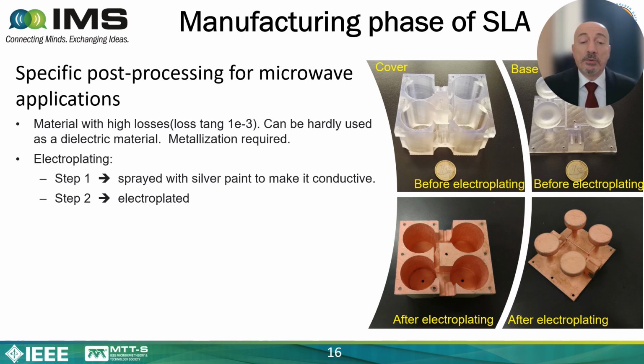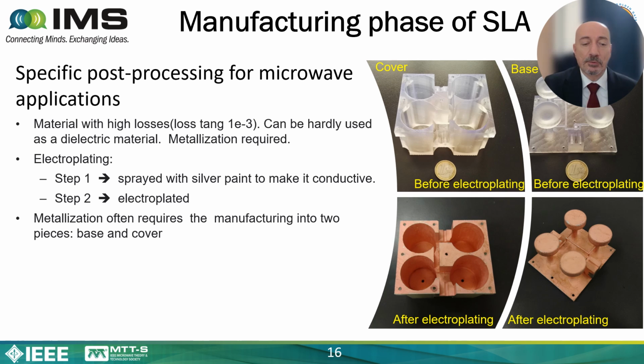Why do we also use the electroplating instead of just using the silver paint? Because the silver paint itself is not very good, because the resistance is quite high. So it is better to use it just to make the surface conductive and then to electroplate, because with electroplating we can obtain much better results in terms of losses. And this is very important because this is a filter, so low losses are very important.